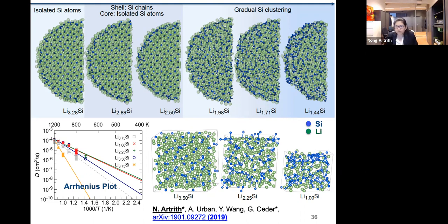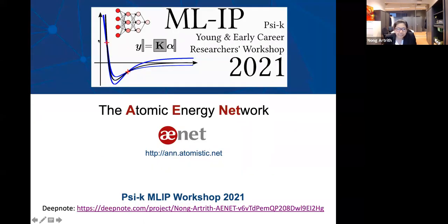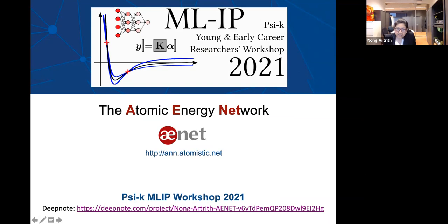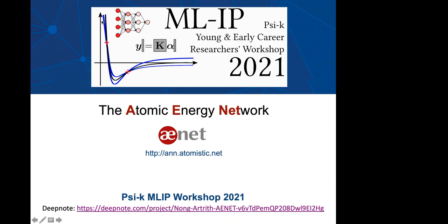So for the repulsive region here, the short distances, you have to include this in the training sets too. Otherwise, it also cannot work. And sometimes, like the simulation that I just showed you, it can also explode. So it's also important to include very compressed structures in the training.